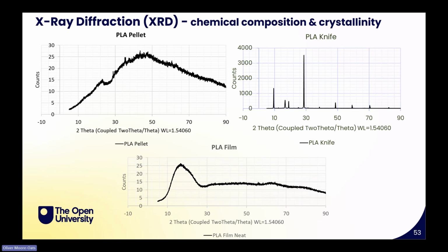Another interesting technique that you can use for identification is X-ray diffraction. So XR or XRD can show chemical composition and crystal structure. Now, crystal structure, or crystallinity in very simple terms, can affect hardness and density, right? So we can see here in the top row that the crystallinity aspect can be between 10 and 30.